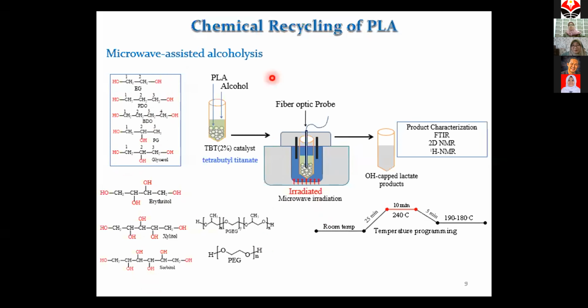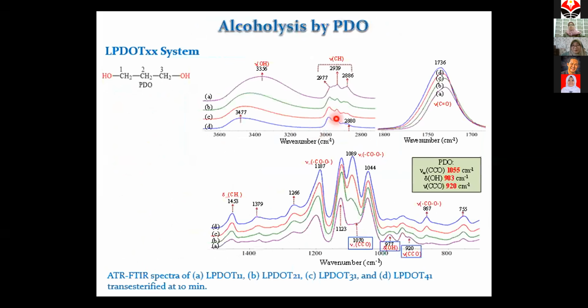From this process, it takes only about 10 minutes to digest the big chain of PLA into small units, completely, in about 10 minutes of reaction. So this is very effective.